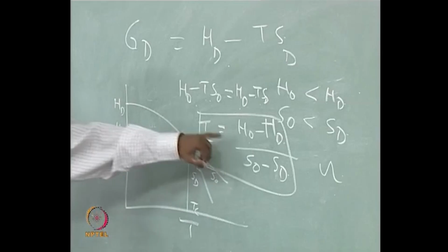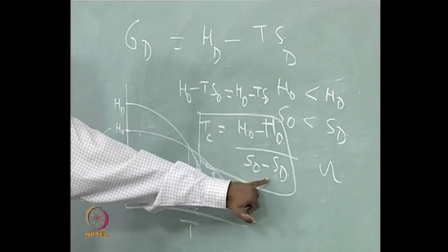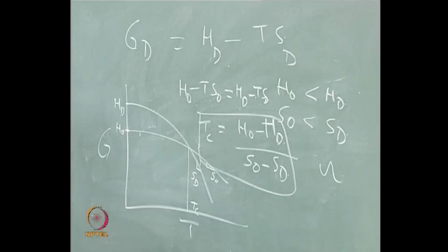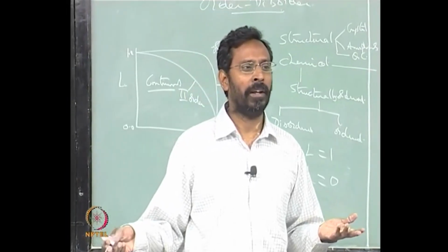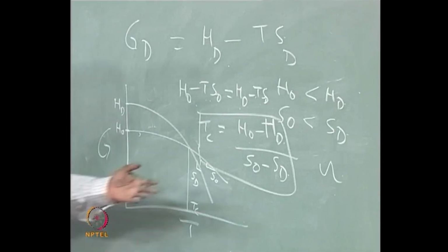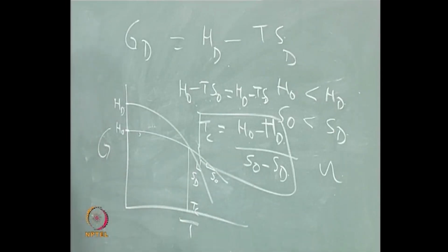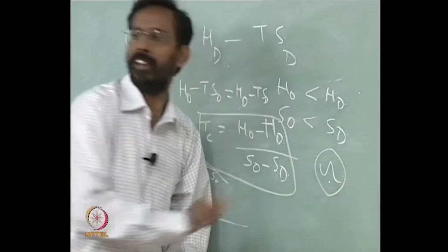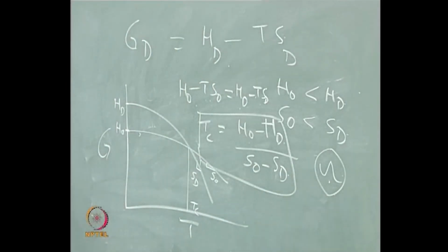and the value of the Tc is again going to be decided by this to a large extent than this, because S of the disorder does not depend on anything, it does not depend on what is A and B, it is simply configurational entropy. If I am taking 50-50, let us say copper zinc, it has a certain value. If I am taking Ni3Al, let us say 75-25, it has a certain value of configurational entropy. It does not depend on whether it is nickel or aluminum or copper or zinc, configurational entropy does not depend on that. So, you can see it is this omega which decides it, that is why in certain compounds the transformation occurs at a lower temperature, in certain compounds transformation does not occur until you reach the melting point.